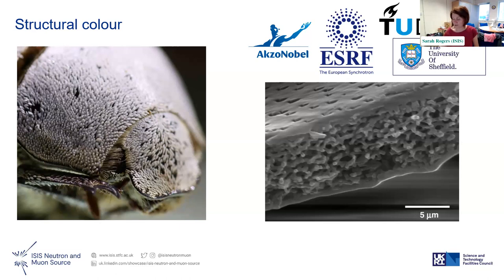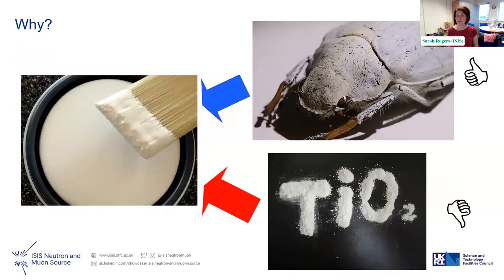And the reason that they're interested in him is because of things like paint. So at the minute with paint, you will use things like titanium dioxide. And clearly that's not great to have lots of nanoparticles kicking about. The way that you make titanium dioxide is not very nice. It kicks off a lot of CO2, I believe. And just having a lot of nanoparticles around is not great for the environment.